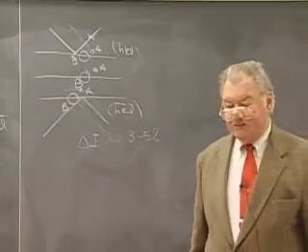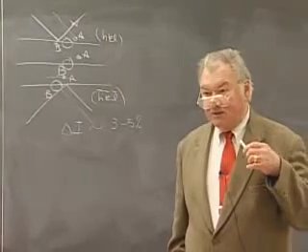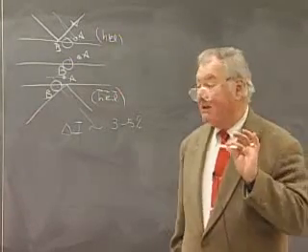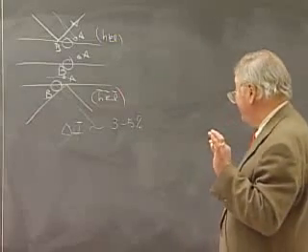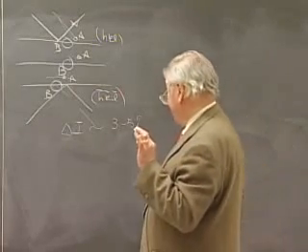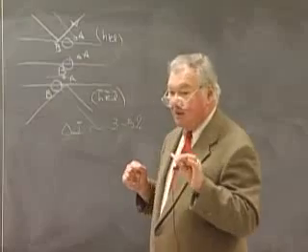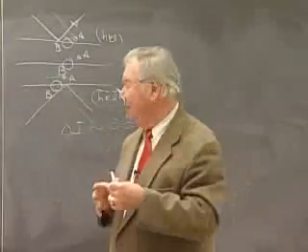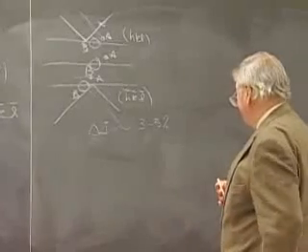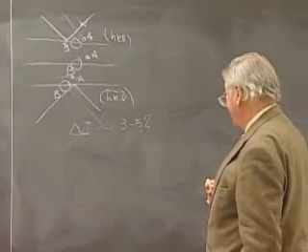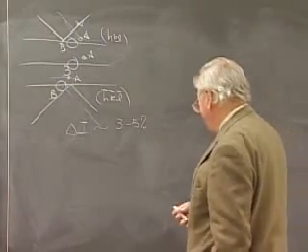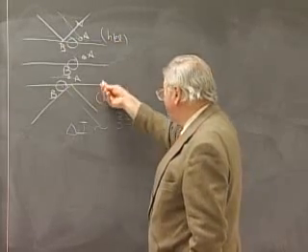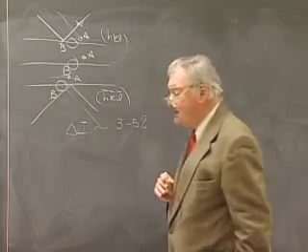But that is something that you could not do until synchrotron radiation came along, when you could actually tune the wavelength to a particular value that you wish to use, and not use something that was spewed out by an X-ray tube that had a target, such as molybdenum or copper or chromium perhaps.